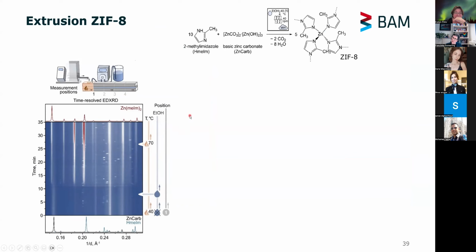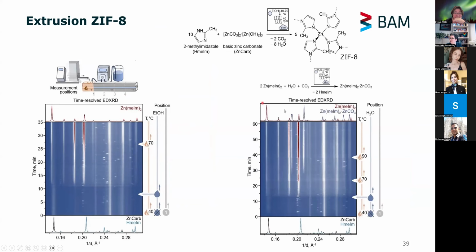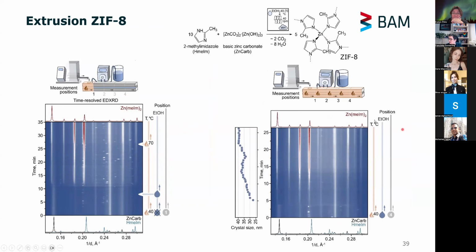In the end, if we change a bit the conditions and use water, for instance, as a solvent, we have this annoying side reaction, but we were also able to optimize it, or we knew how to optimize it upfront. And you can see here under the optimized condition, it's a fast reaction. Within 25 minutes, you have your final compound.